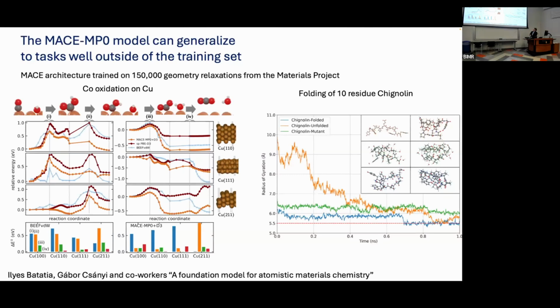Here what you're seeing is the reaction coordinate and the relative energy of the barrier, and a comparison of MACE with dispersion correction, PBE with a dispersion correction, which is exactly the same functional that MACE was trained to, plus this BEEF-vdW functional that's been used in the field of heterogeneous catalysis. And what you can see is that in some cases, like the Cu surface 110, it maps the barriers pretty well, even though it has never seen up to this point any sample that would look like this. It's only seen solid state inorganic materials.